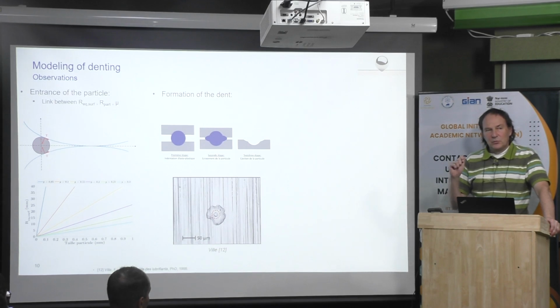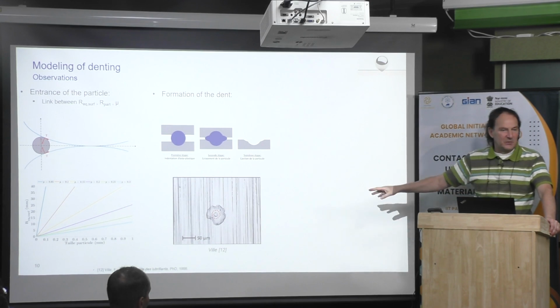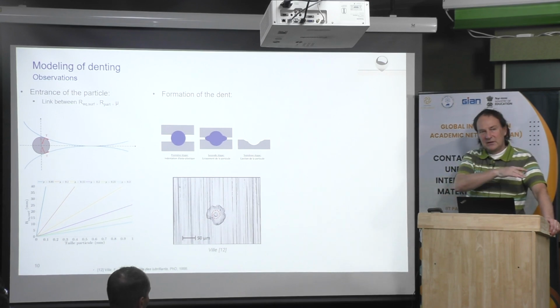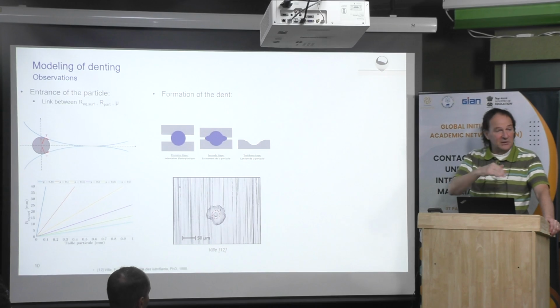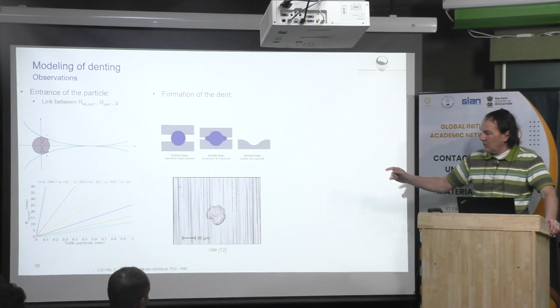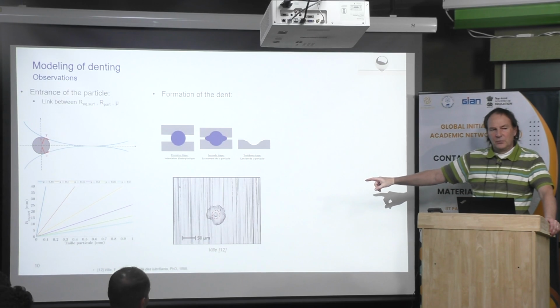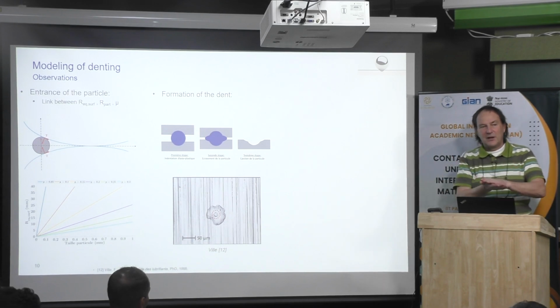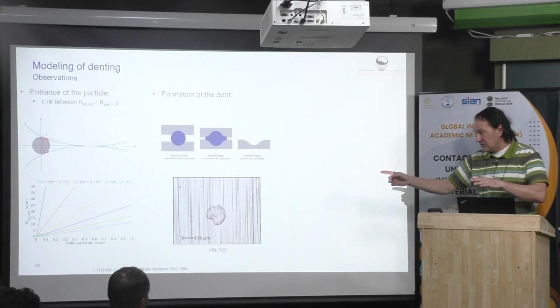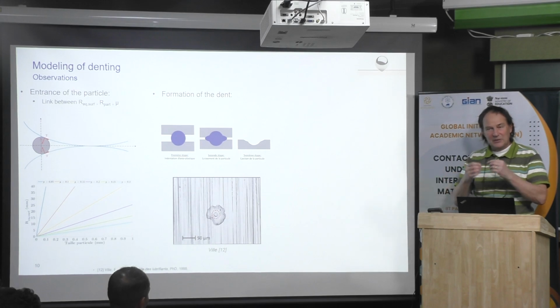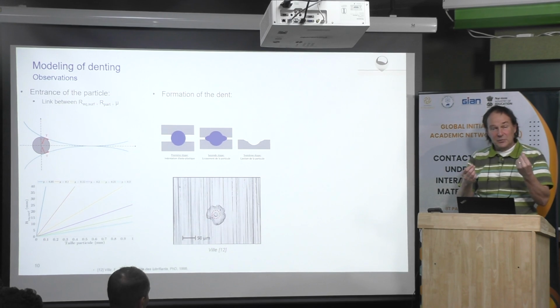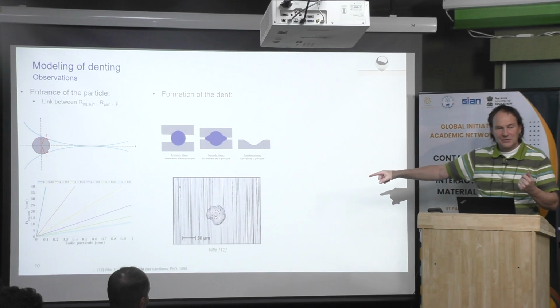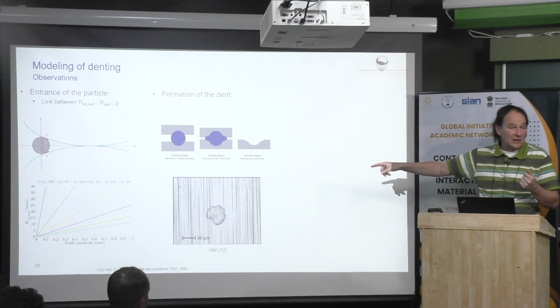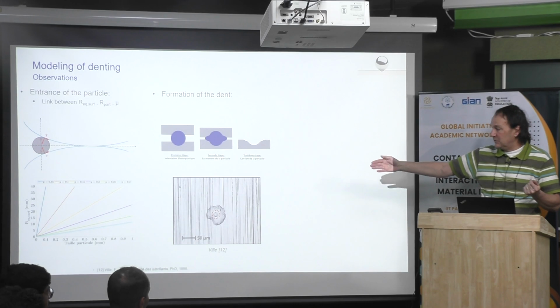Very often, now I don't do any more experiments, but my colleagues are still doing what I did in the past, same procedure. In fact, when you dent a surface, you know that you have action-reaction, then the opposite surface, which is flat, will see the same pressure. Okay? However, the opposite surface has not been hardened by the denting, because here there is some plasticity around the dent that can protect the dent, or even you can have the dent failing.